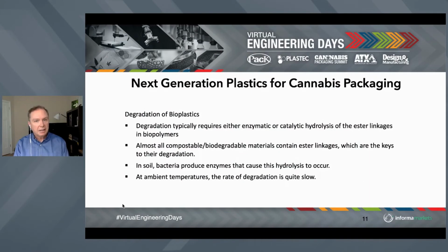So the degradation of the bioplastics, if we're going to get into a little bit of chemistry here, typically requires enzymatic or catalytic hydrolysis of ester linkages in the biopolymers. Most biopolymers have these ester linkages associated with them. And these ester linkages, which you'll see in the materials that I'm getting ready to talk about, are the keys to their degradation. In soil, bacteria produce enzymes that cause this hydrolysis to occur. If you have it at ambient or room temperatures, the rate of degradation can be quite slow. As you increase the temperature, increase the moisture content, the rate of degradation increases as well.